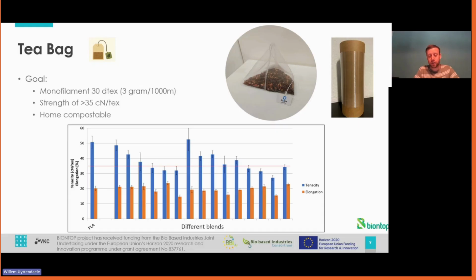fibers that weigh, just to give you an idea, 3 grams for a kilometer of fibers. So these are really extremely thin, but they need to be quite strong to keep the tea inside, to keep their shape, and be home compostable. And by starting from a PLA and mixing it with different blends of other biopolymers, we could get to a material that is both home compostable and meets the strength requirements of these tea bag fibers, which is 35 centinewton per tex. These were then further commercialized by Sioen and are on the market now as home compostable tea bags.